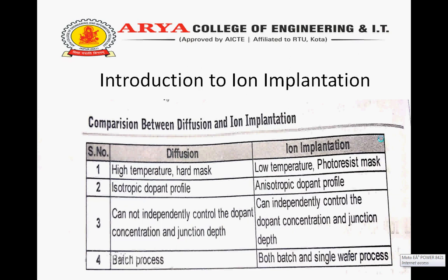If necessary, a particular ion species is selected by appropriate application of a magnetic field. The charged particle species are then focused to form an ion beam, which is accelerated by suitable application of an electric field and made to scan a target area by a suitable electric field. This ion or electron beam can be easily directed by an electric field. The directed ion beam is used primarily for two purposes.